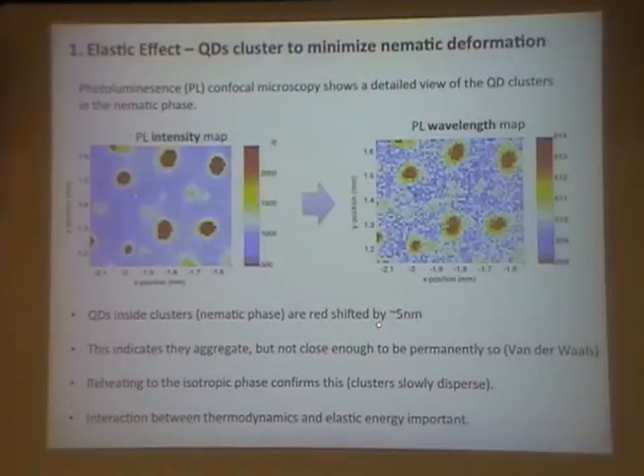It's actually redshifted by about 5 nanometers. First of all, we're thinking, well, it's a bag of balls assembly, permanently stuck together. But actually, this is not a very big redshift. The amount of redshift you get can be characterized by how far apart the particles are, so by looking at this number, you can back out the separation of the quantum dots. And we can tell that they're not close enough to be permanently aggregated.